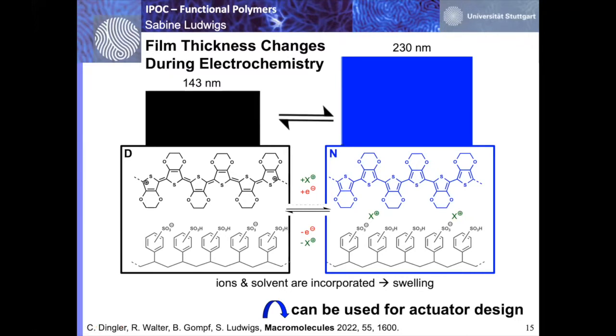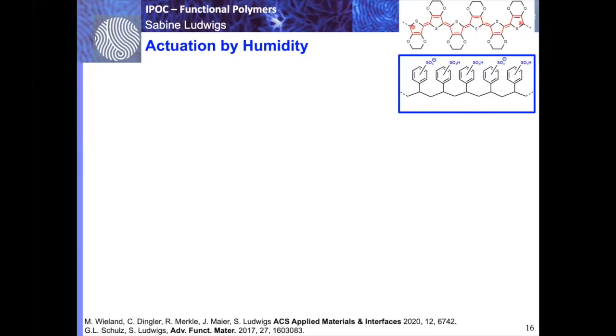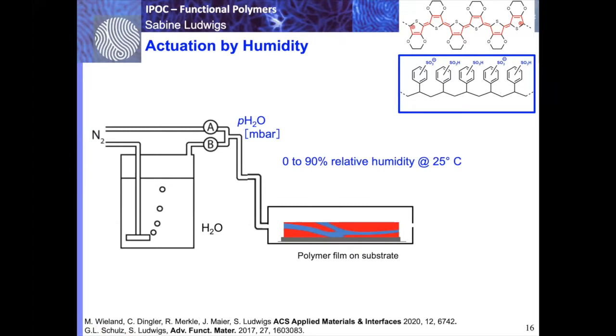I'm not going to talk about this electrochemically induced doping in this talk, but I want to switch to an easier stimulus, and that's the stimulus of humidity. And for that, I'm just using essentially the PSS compound in the PEDOT:PSS, because you remember I said that's a polyelectrolyte. We have self-made chambers where we create relative humidities between 0 and 90%, at 25 degrees. So we can tune the relative humidity, which means we can tune the environmental conditions reliably. And we do that by mixing nitrogen streams, a pure nitrogen stream, which goes through line A, and a nitrogen stream, which bubbles through water and makes a saturated water atmosphere. And then by mixing these two streams, we can define the vapor pressure in self-made chambers, which then relates to the relative humidity.